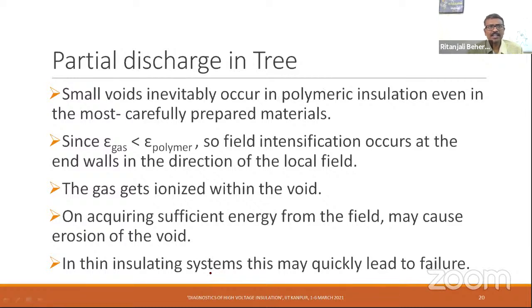Partial discharge in trees: small voids inevitably occur, as I have mentioned. Since the permittivity of the gas is much less than the permittivity of the polymer, field intensification occurs at the end walls. In other words, the void gets more stress compared to the solid insulation, and hence partial discharge takes place within the void, and this is a very repeated activity. This gives a lot of opportunity for ionization to take place, and upon sufficient energy, the electrons carbonize and break the walls of the void, leading to the tree channels, and then finally to the failure.